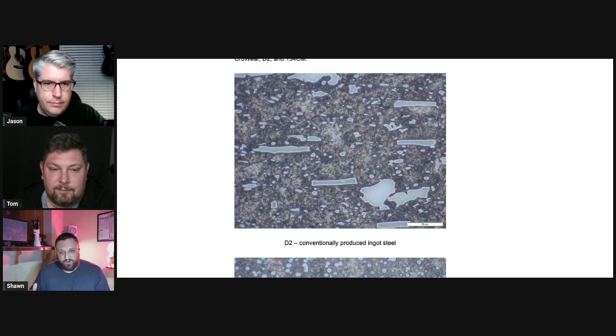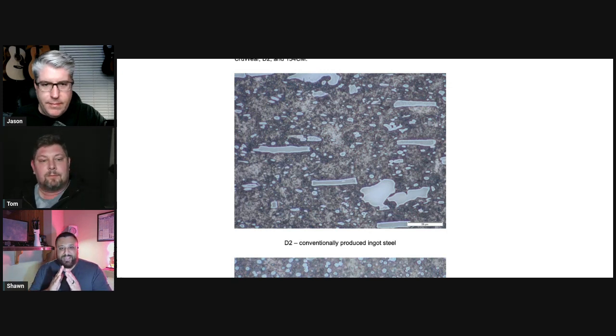So the bigger they are and the more stresses we put on them, especially at a thin cross section of an edge, which can be a nanometer section that's significantly finer than the micron. It takes 1,000 nanometers to make 1 micron. Problem there is now it's a lot easier to break out that edge. Yep. You have less toughness at the edge, but also the bulk blade material is going to be easier to fracture and break because we have these pockets here. We have these big elongated brittle regions.